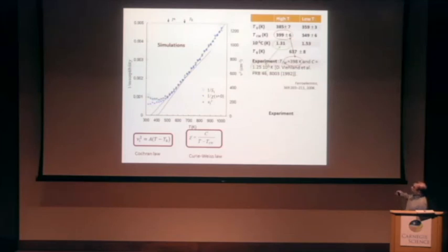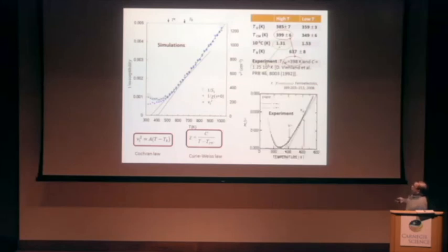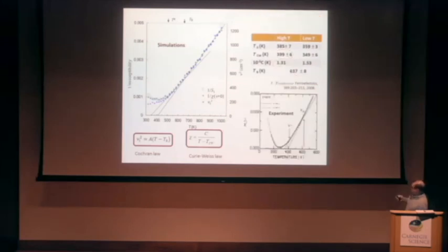We see a very good Curie-Weiss law at high temperatures, and a very good Cochran law, which completely corresponds to the Curie-Weiss law. The Curie-Weiss temperature and Curie-Weiss parameters are very close to the experimental results for the Curie-Weiss law. And below the T-star temperature, we observe the second Curie-Weiss law and the second Cochran law.